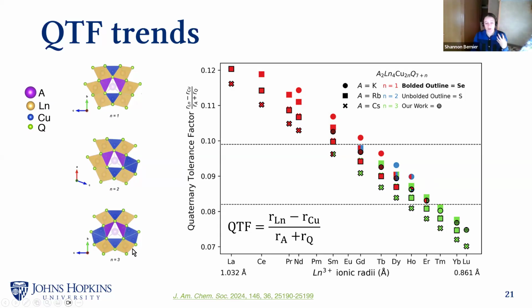So the mixed phase region here is where any of these bonding environments are favorable, but on either end, when the lanthanides are very large, the copper selenide will either only be added, which is this case, or it will not add into the structure in this particular location here for the low lanthanides. So the quaternary tolerance factor, which is detailed a lot in this paper, does a really good job of sorting this way, and it's talking just about bonding environments. So if we're not talking about bonding environments and instead we're looking at the unit cell as a whole and talking about its shape, that is what the cubic deviation metric ought to do.